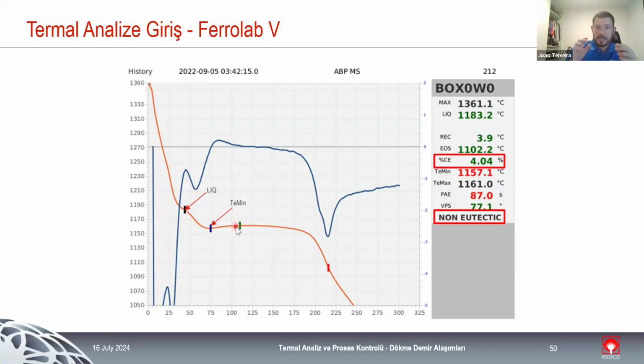The first derivative is, every time we have an inflection in the main curve, we have a zero, so we have a change of direction in the first derivative. It's just for us to have higher control of the points where some changes happened. For example, here we reach liquidus temperature and we have a change in direction. We achieved the minimum temperature. We have another change in direction. And you can see all the different parameters that we can control with thermal analysis.